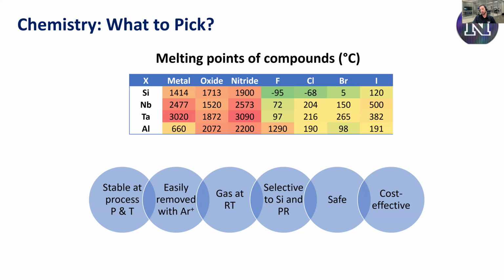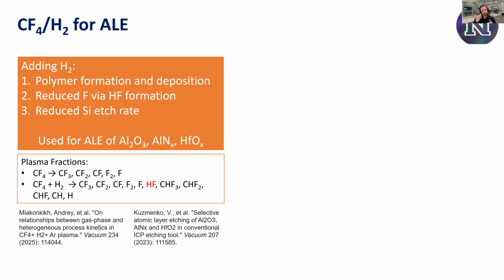But the problem is, how are we going to get selectivity to silicon? We don't just want to get through our material and then start blasting through the silicon in the system. So we're going to consider adding hydrogen. This is a little bit different from the ALE I described before, because we're actually going to get polymer formation and some deposition in some cases. If we want to control the amount of spontaneous etch of silicon afterwards, we're going to need to control the amount of free fluorine in the gas phase during the dose step. So we're going to do that by adding lots of hydrogen to form HF.